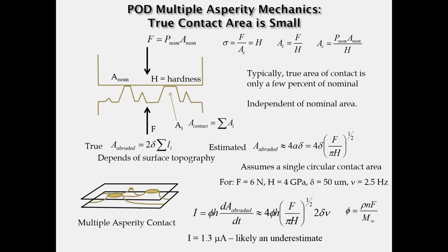When you go to a multiple asperity test, you can see now if you have two surfaces in contact, you can have two areas or multiple areas making contact, but that will be much less than the nominal area. Again, the area of contact will be given by the ratio of the force across the surface and the hardness of the surfaces that are engaging. From that, you can come up with some estimates of the area abraded and make an estimate of the currents that are generated. And these currents are, again, right in line with the currents that we measure for these kinds of contacting interfaces.